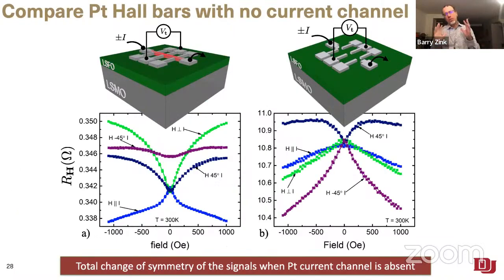But again, one thing that's very clear is we know we have charges flowing around in all this stuff. This LSFO layer is simply not providing a real insulating barrier between the charge. What that means is that some of the current that we're putting into this platinum is definitely getting into this LSMO layer, because it's quite a bit thicker than either the platinum or the LSFO layer, conducting through that LSMO and then getting back out the platinum and causing some of these signals. We don't know quite yet how much, and that's part of what we're trying to figure out.